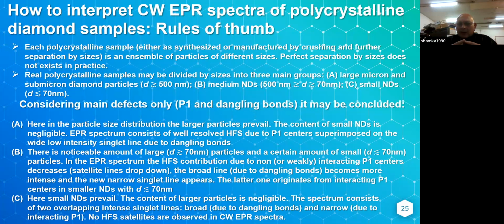But for group B, when you start crushing your large particles, you have a noticeable amount of large particles above 70 nanometers and a certain amount of small particles with sizes below 70 nanometers. In the EPR spectrum, you have a decrease of the hyperfine split contribution due to weakly interacting P1 centers in larger particles. The broad line due to the dangling bonds becomes more intense because of the decreasing sizes. And the narrow singlet line appears, which also increases when you go to smaller sizes. The latter narrow line originates from interacting P1 centers in smaller nanodiamonds with diameter below 70 nanometers.